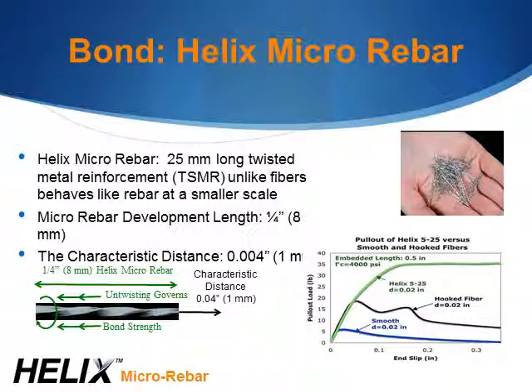People have been trying to do this with concrete for literally centuries, but the problem is anything that you mix with concrete, its behavior is fundamentally governed by friction. And friction is just a function of how much surface contact there is between the reinforcing element and the concrete. With Helix, we've changed the failure mechanism from friction to actual untwisting. So if you go on our website, you can actually see a piece of Helix untwisting as it comes out of the concrete. That untwisting motion provides a constant level of resistance, regardless of the strain in the system. Steel fibers, which Helix somewhat resembles at first glance, behave in a much different manner because they're governed by friction.